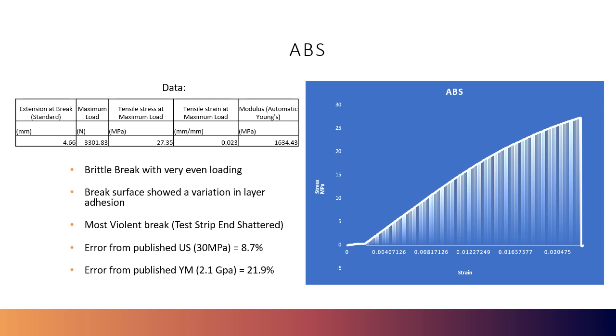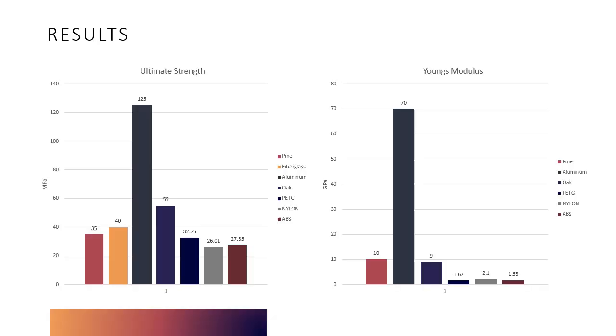Okay, ABS. I was able to find the specific filament data for this material as well, and the variations from the published numbers aren't too terribly severe. My Young's modulus is quite a bit lower, which I think is due to the layer delaminations, which you saw again on this particular test strip. So I'm imagining it just didn't have the stiffness to get up near those correct numbers. But yeah, it broke brittly, shattered pretty severely at the end of the test, and was very middle of the road as far as its properties.